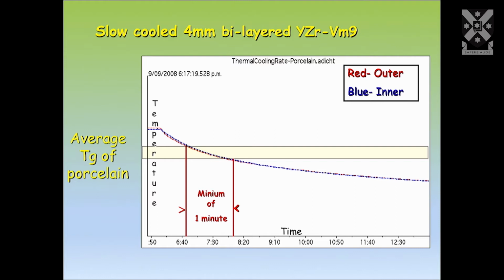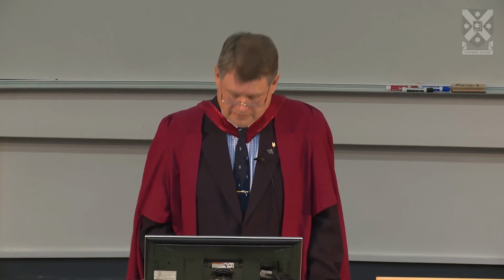And we moved to publish this very quickly because this was still a worldwide problem. And Otago was instrumental in the manufacturers worldwide changing their firing cycles to include a slow cool cycle on the last thermal cycle of the firing of the porcelains when you veneer it. And the manufacturers were very grateful to us because dentistry was about to walk away from zirconia because of these failures. And we were able to say, listen, here's the solution to the problem. You can keep using it.